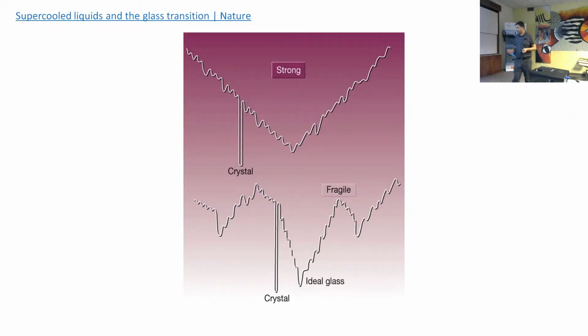And in this picture you have the landscape. You see that in a strong glass former, you have a minimum of energy, and you have the minimum of energy of the crystal, but it's quite well behaved. So if you cool fast enough, you avoid this trap to form the crystal, and you have a very stable amorphous material. While in a fragile glass former, you have many different traps that can make these barriers smaller, and so the fragile glass formers are more difficult to manipulate. And remember that polymethyl methacrylate is a fragile glass former, and it is used to make luminescent solar concentrators.